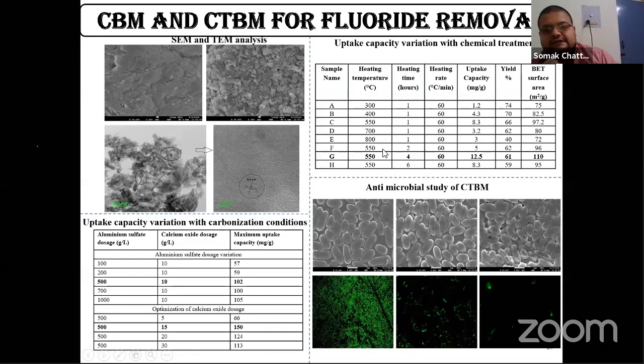So we saw that once the heating time was increased, at 550 with 2 hours, we were getting 5 milligram per gram of uptake capacity. Now, when it increased to 4 hours, we got 12.5. Now, what is the reason for this? More increase in heating time will lead to the preparation of more crystalline structure. But again, there is a certain bar to it. If you go beyond a certain time scale, it will again turn itself down, or a part will turn itself down to ash. So once we exceeded 4 hours and went to 6 hours, it decreased to 8.3.